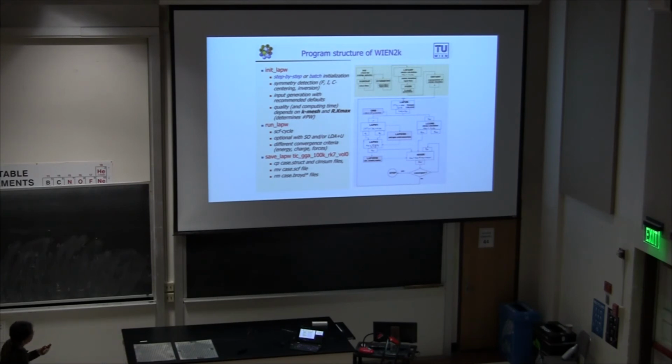However, this was the way it was done maybe a couple of decades ago. More recently, because now we have computers, you can write more sophisticated algorithms. You can calculate the valence bands, you calculate the core levels, and there's something called a mixer, which is in fact the most computationally expensive part of these codes. It's the part that starts mixing the core levels and the valence bands, but this has to be done very carefully. You should not leak too much charge out of the Muffin Tin radius, and all of this you have to control when you're doing the calculations. You should constantly check these things. You can calculate the band structure, but it may mean nothing at all. So it has to be carefully done.